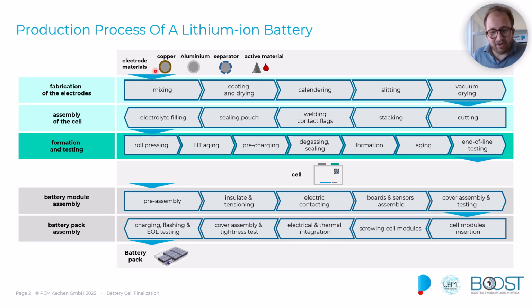First, I would like to define what the formation is. The formation is basically the first charging and sometimes also a few charge-discharge cycles of the cell. And during this process, a lot of electrochemical reactions occur inside of the battery cell, which weren't possible before. So mainly it's forming the solid electrolyte interface, the SEI I already mentioned, on the anode side. And without that formation, basically the battery cell would not work in a proper way and could not be used for a long lifetime. Hence, this is a super important process of the battery production.